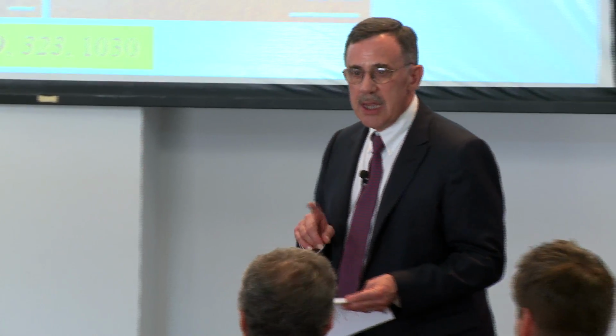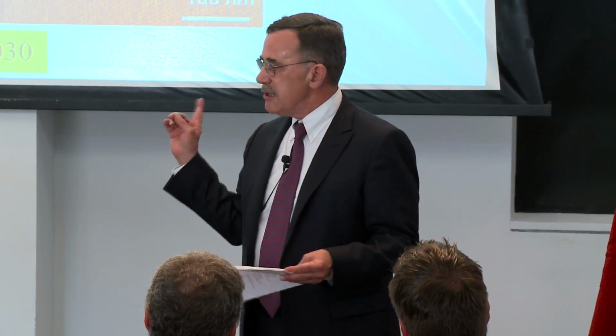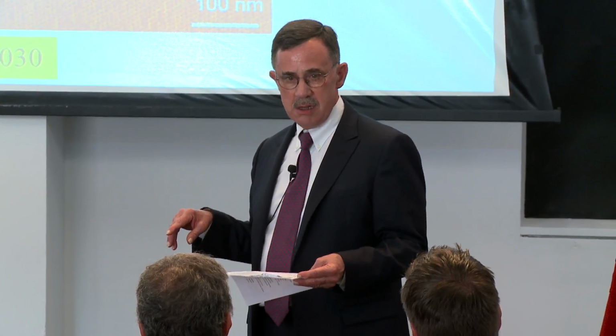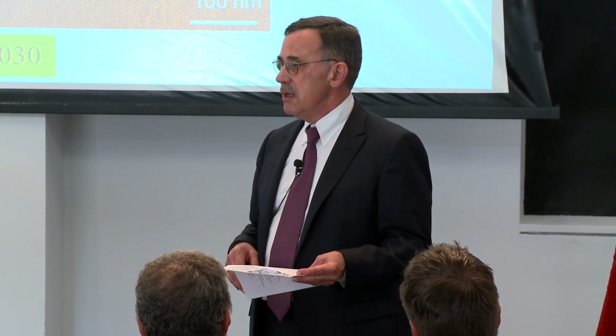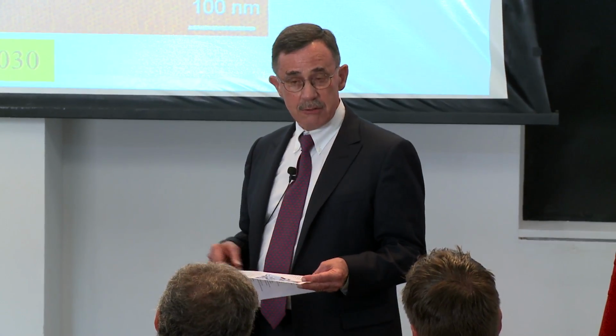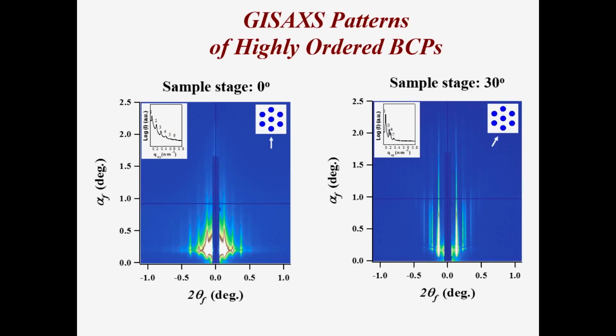This, however, is independent of where you are on the surface. And this surface happens to be a reconstructed sapphire surface, which gives you these very small facets on the surface. And we've used this to bias the orientation of these hexagonal arrays on the surface. If you look at that image, and if I were to do grazing incidence X-ray scattering, I could take the surface and I could rotate it. And you have a hexagonal array in 2D. You have the 1-0 planes, and you have 1-1 planes. So those are just crystallographic planes. I can rotate the surface, and I can look right down a 1-0 plane.